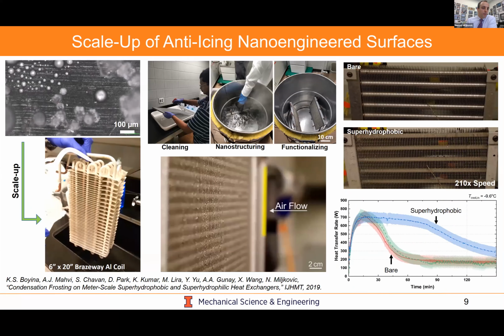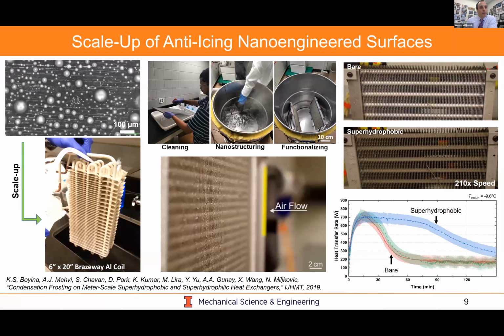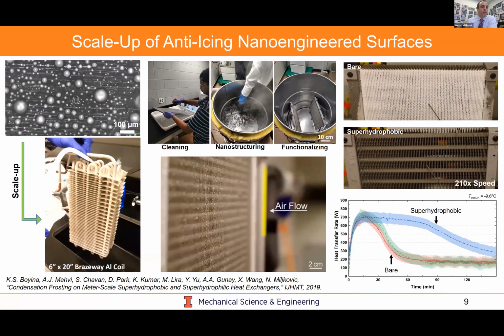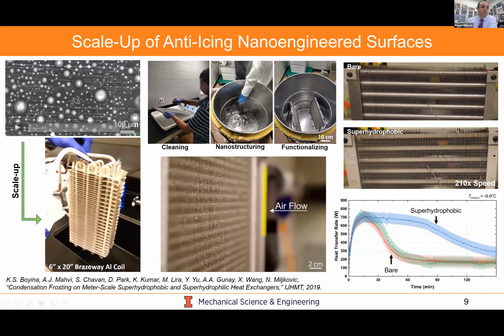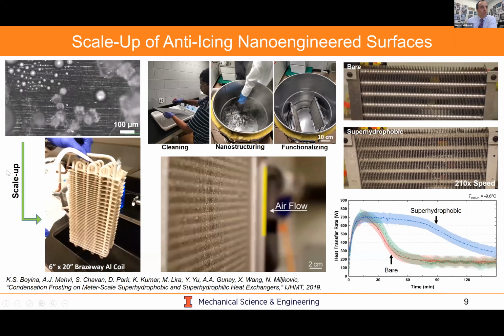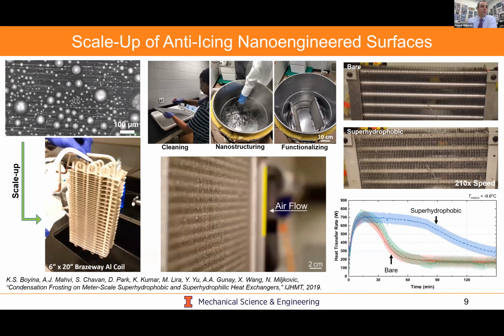Now, Demos did a great talk on icing. One area where we've had contributions is looking at scale up of passive anti-icing surfaces. So these are a little bit different from what Demos discussed. Dan discussed this a little bit in the beginning, where we use coalescence-induced droplet jumping on superhydrophobic surfaces to actually remove supercooled droplets from the surface before they could freeze.